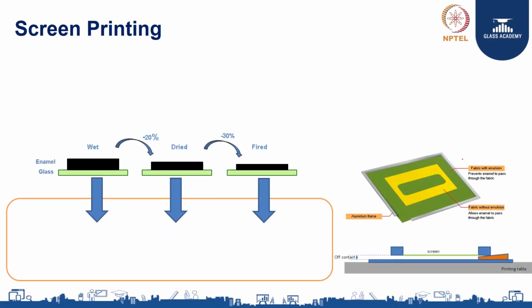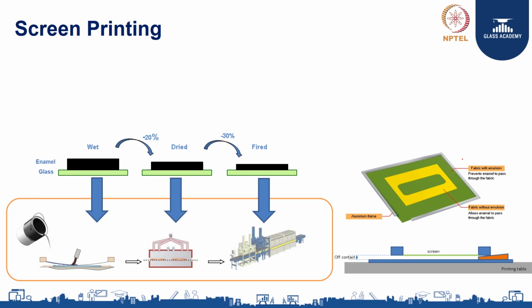So let us discuss first the screen printing. Screen printing is nothing but a mesh, like a screen, fabricated with the help of aluminum around the periphery in a tight manner. You can see here we are applying the paint, basically a ceramic glass frit with pigment, mixed in proportions according to the thickness you want, and you pour it on top of the screen. You see that the drying process is happening. After that, it will be a firing process.